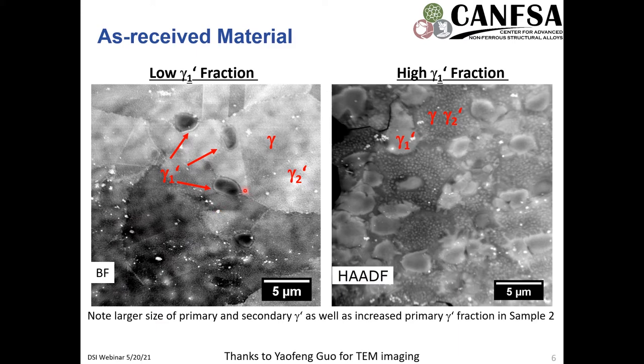And on the left here, we have the gamma grains that are about 5 to 20 microns in diameter. And we have the primary gamma prime that's on the order of about 3 microns in diameter. And the secondary gamma prime is about 20 to 50 nanometers in diameter. As opposed to the microstructure on the right, we have a higher fraction of primary gamma prime that's about 3 to 5 microns in diameter, and we have a coarser secondary gamma prime that's about 100 plus nanometers in diameter, and the gamma grain size is nominally smaller, about 5 to 10 microns in diameter.